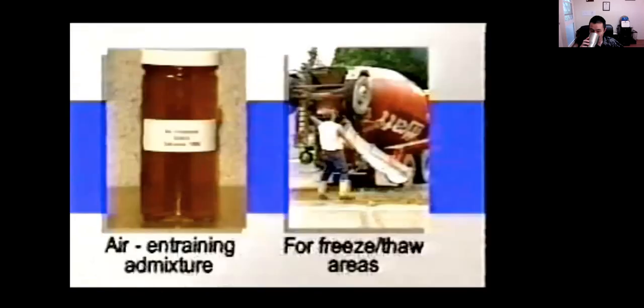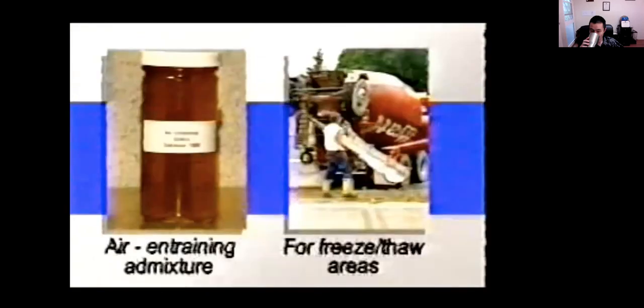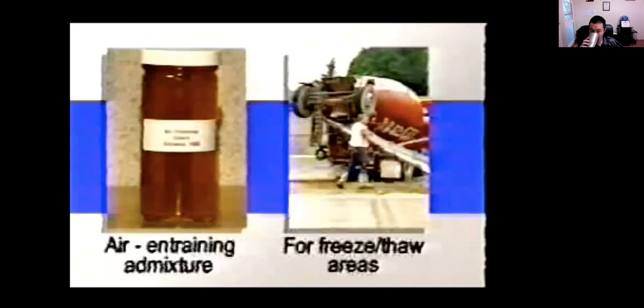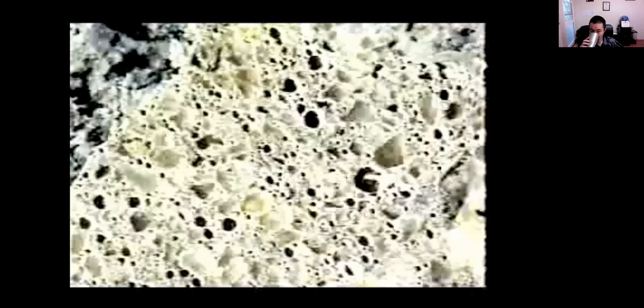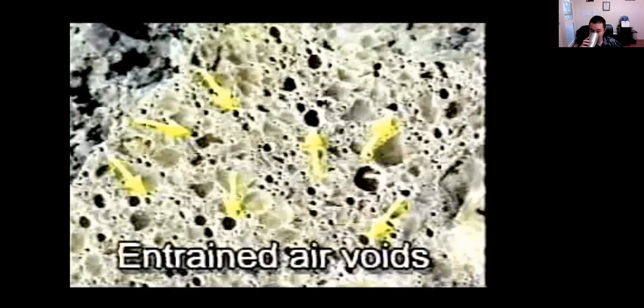For quality concrete in freeze-thaw areas, an air entraining admixture should be added to the mix. Entrained air provides millions of microscopic bubbles of stress relief when water freezes and expands. Air entrainment is what makes this weather-exposed Chicago driveway different from the floors not exposed to the weather in this multi-story building, and even this driveway in Florida, which isn't exposed to the many freeze-thaw cycles.